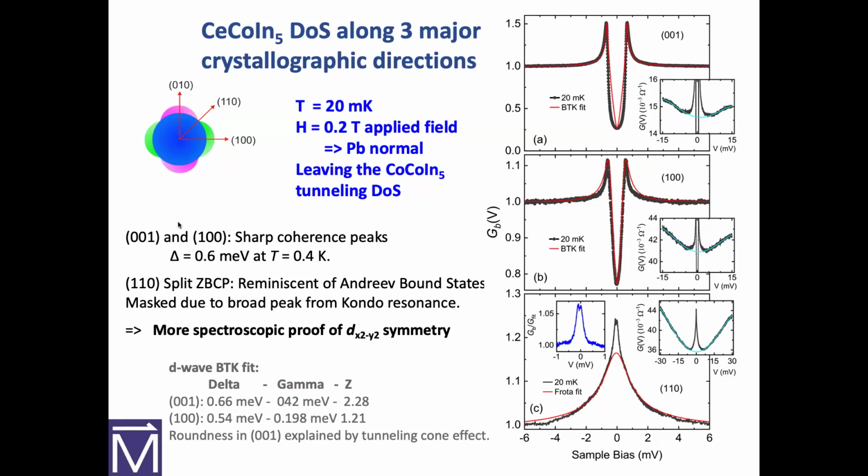The electron coming in and the hole that's retroreflected feel some of this coherence. Within about a coherence length of the superconductor, where it's exchanging these electrons for holes, you have reduced the superconductivity. So the microscopic explanation of the superconducting proximity effect is Andreev reflection.